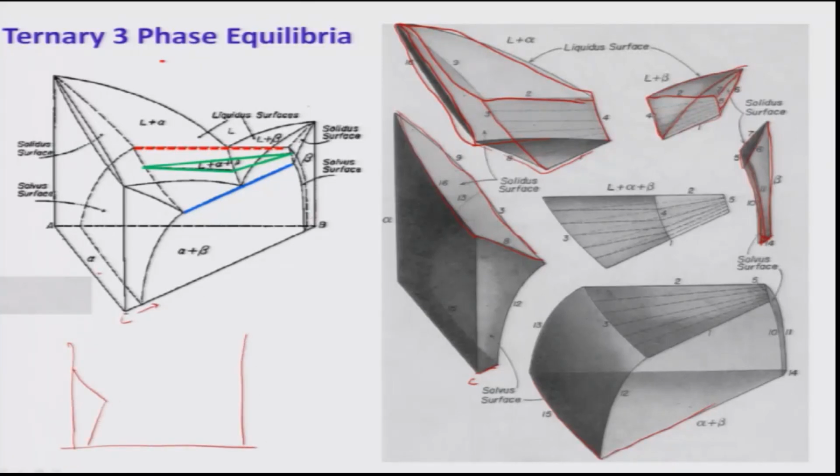In a binary, normally we can discuss 3 different types of alloys, okay. So, one is this, other one is this, and third one is this or this. So, what are these called? This is eutectic, these are hypo or hypereutectic, and this is well inside this alpha phase field. Same thing here can be done. So, we can discuss alloy composition same as eutectic, one of the eutectics. We can discuss this alloy composition a little bit away from the eutectic, but well within the two phase region, and third one is obviously same as I told you just now, within the alpha.